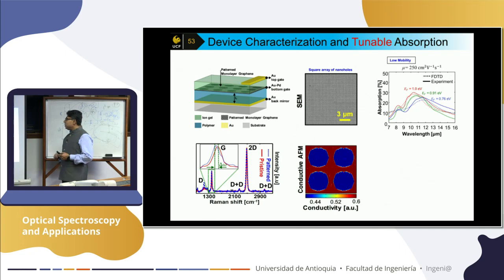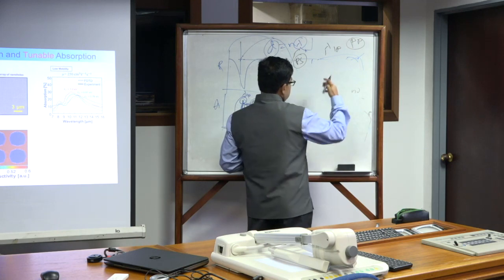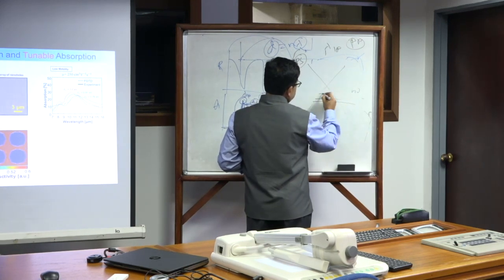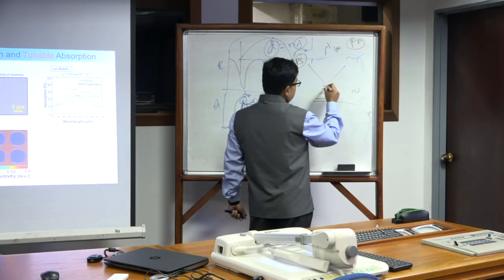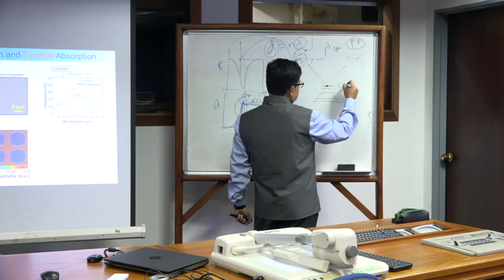Next step, to show that we could electronically change this conductivity by applying a gate voltage. If you are familiar with a gate, this is your graphene film. You put a dielectric spacing layer, put another electrode on top and apply a voltage, creating a capacitor actually. The capacitor has a field, and the field draws electrons from the surrounding medium. In this case, I think there is an aluminum oxide layer, and you can change the electron concentration on the graphene, changing the Fermi level on the Dirac cone. So what you are doing is changing the Fermi energy of the graphene. This is the Dirac cone, and we started here, and then you slowly change. You go closer to here, called the charge neutrality point, meaning almost no carriers. That's the CNP, or Dirac point.